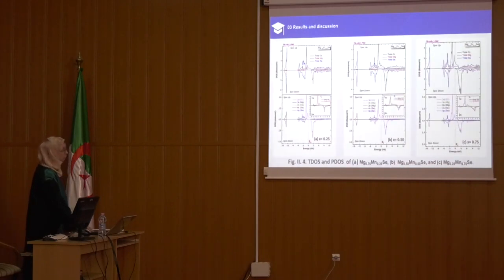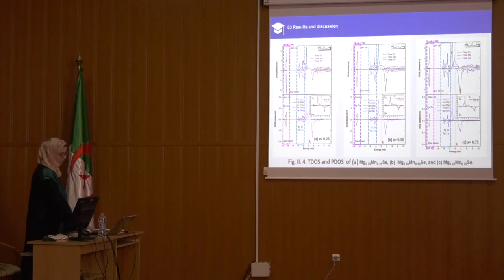Here we have the total and partial density of states for each concentration. We observe that for all three compounds, the lower part of the valence band, between -15 and -12, is occupied by Se 4s states for both spin cases, while the middle part of the valence band, in the energy range between -7 and -3.5, is formed by manganese 4p and 3d states.